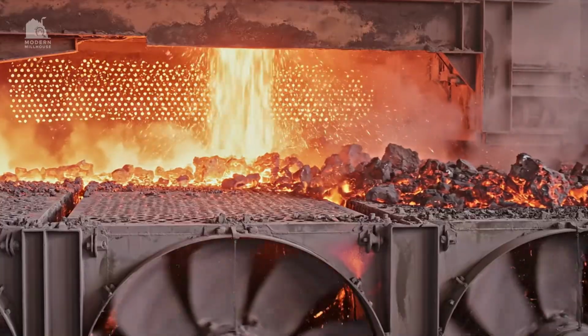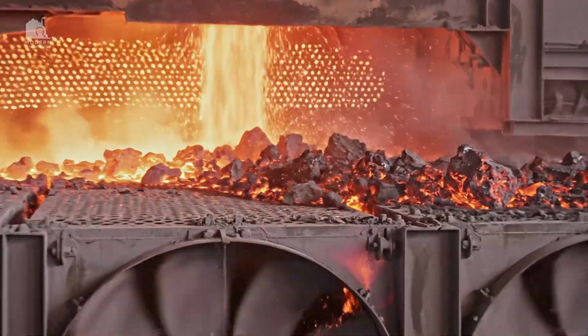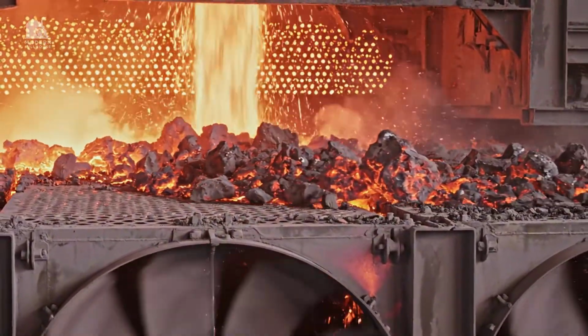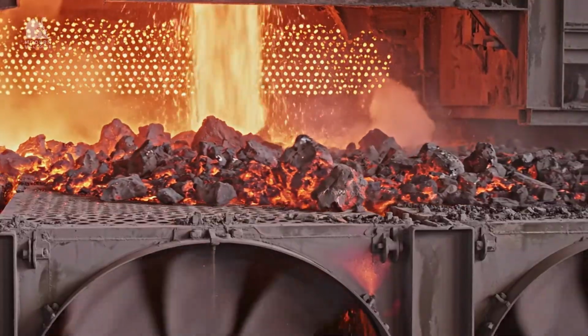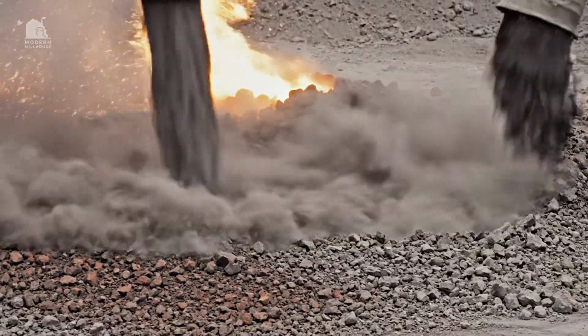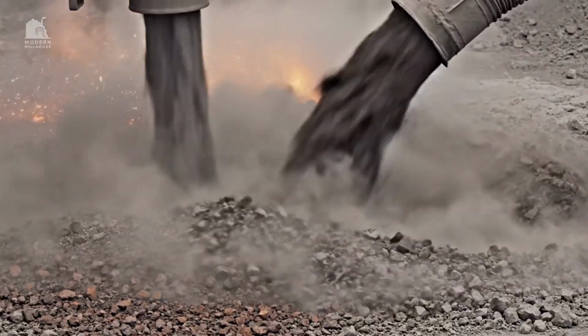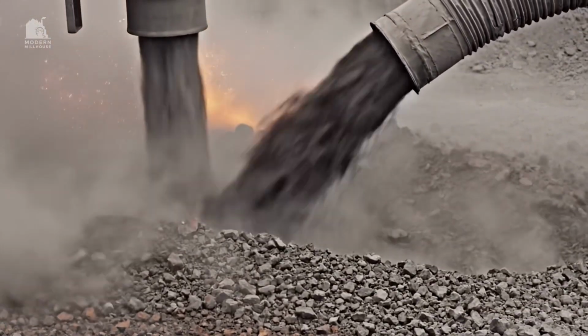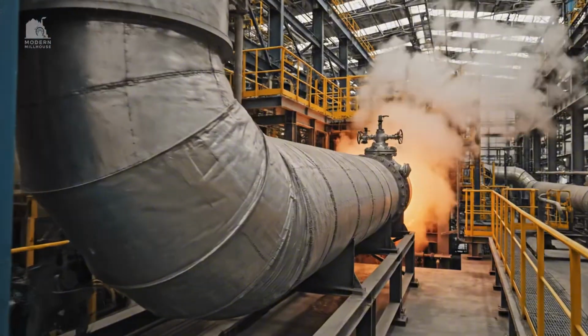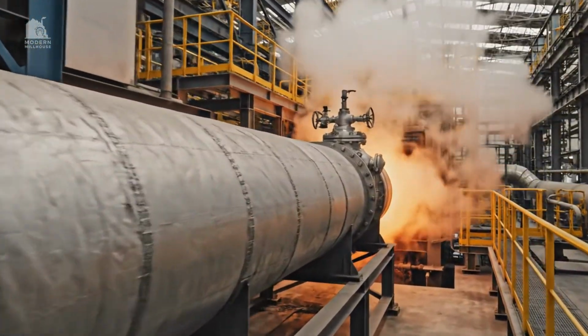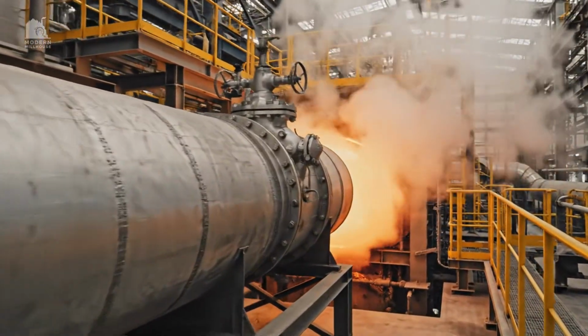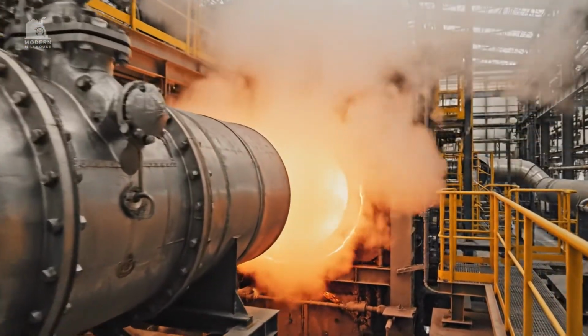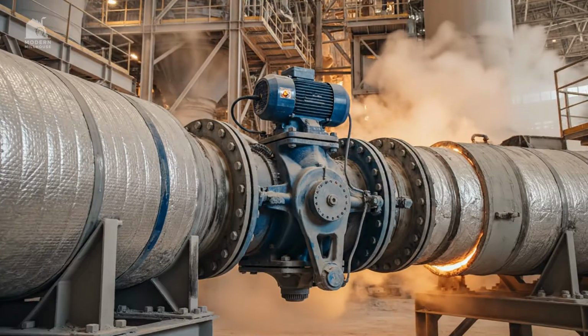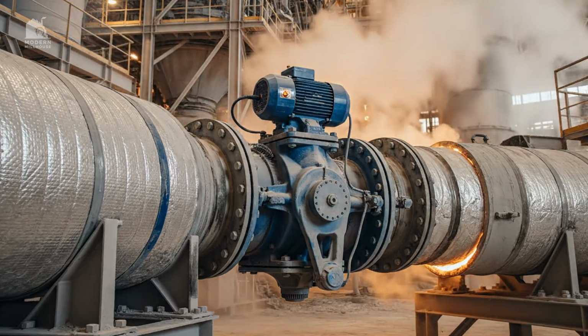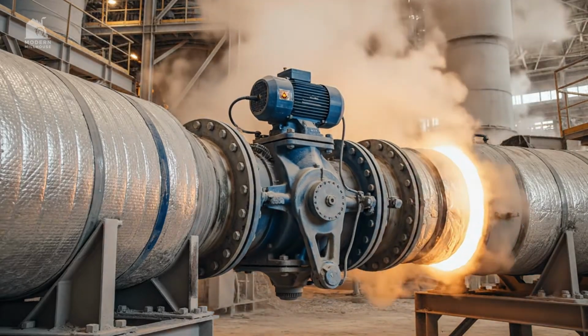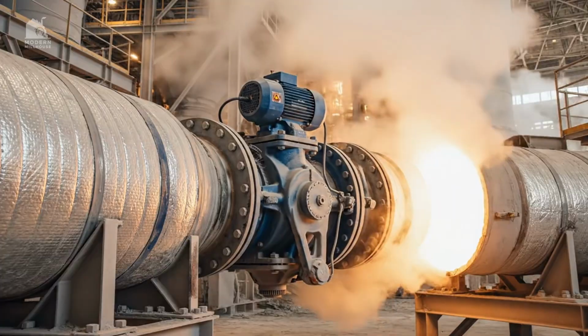The grate cooler forces air through hot clinker, dropping temperature quickly while capturing heat into the airstream. The hottest recovered air becomes secondary air for the kiln flame, reducing the amount of fuel needed for burning. By recycling clinker heat, the plant turns waste energy into useful combustion air, improving overall thermal efficiency. A portion of hot air is diverted as tertiary air to the calciner, supporting calcination without extra fuel.